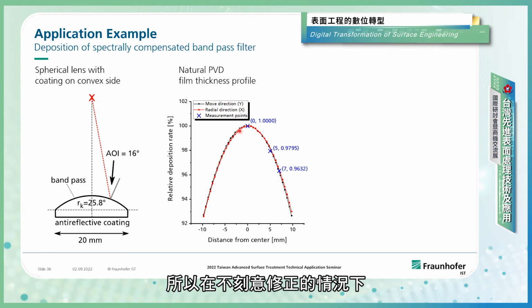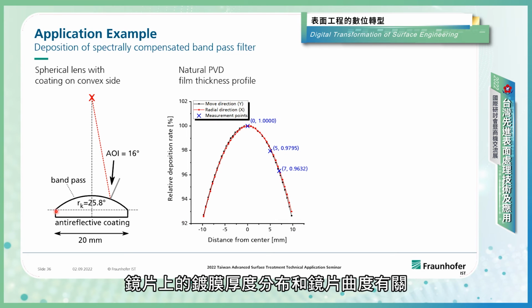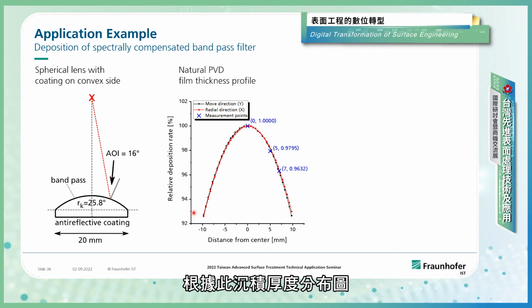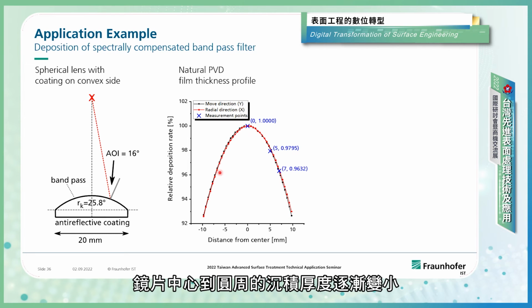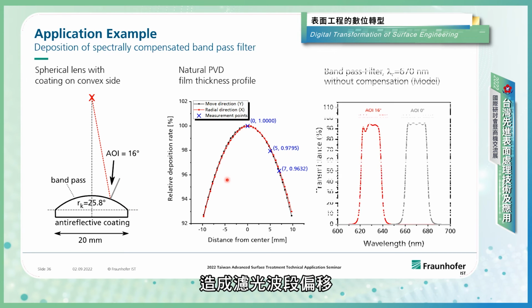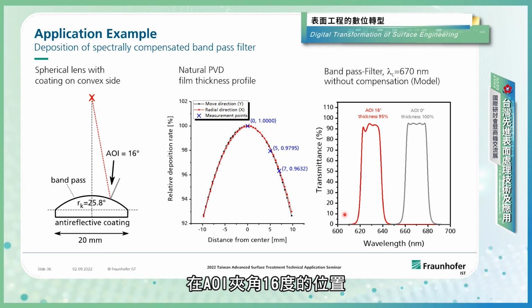Even by the natural situation, depending where you are due to the curvature, you get a deposition profile, a deviation from the 100% rate due to the curvature of the system. And this will result in a shift of your peak, and that might be quite significant if you have 95% thickness. So here, and that's not even the outer radius, instead of a maximum of the bandpass filter of 670 nanometer, your maximum will shift to 630 nanometers. And you want to compensate this and take account for this in a real-time model.